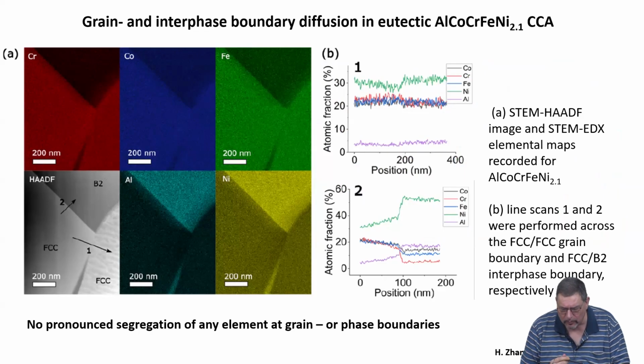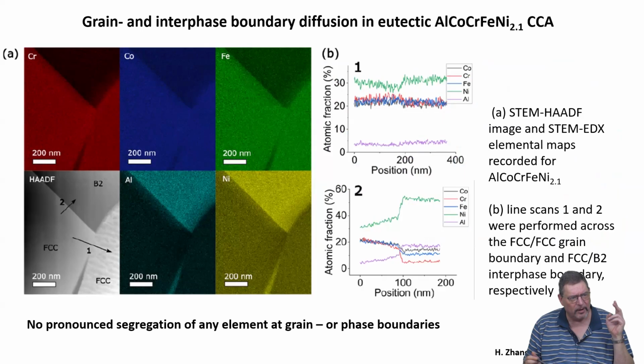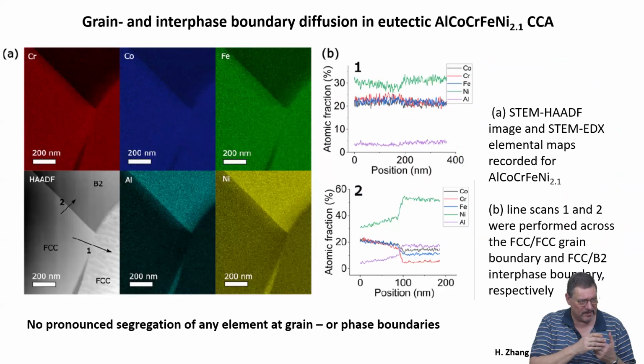And now we have to look a little bit careful because we have now three interface types. We have grain boundaries in the FCC phase. We have grain boundaries in the BCC B2 phase. And we have interfaces between FCC and B2.